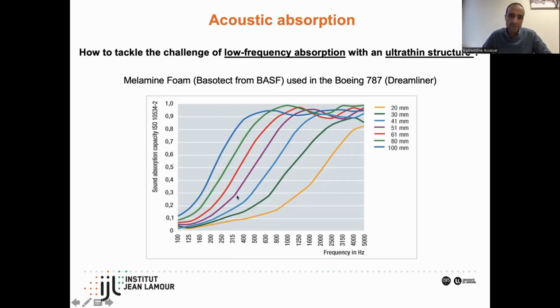You can get like 80%, 90% absorption. However, when it comes to this extremely challenging frequency range, which is basically below 300 hertz, even if you take 100 millimeters, 10 centimeters thick, you cannot get more than 10% or 20% absorption. So this is a real problem. And the idea is how we can use artificial materials, which are metamaterials or metasurfaces, to deal with that.